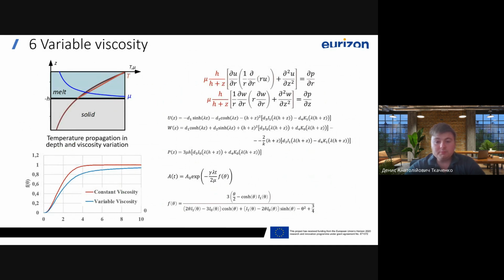In the heat treatment of plastic surfaces, the temperature distribution follows a heat flow equation, and in the molten surface layer, it's approximately linear. If fluidity is assumed to be proportional to temperature, viscosity varies from a finite value on the surface to infinity at the solid phase. In this case, the governing differential equations are modified to account for the variable viscosity.